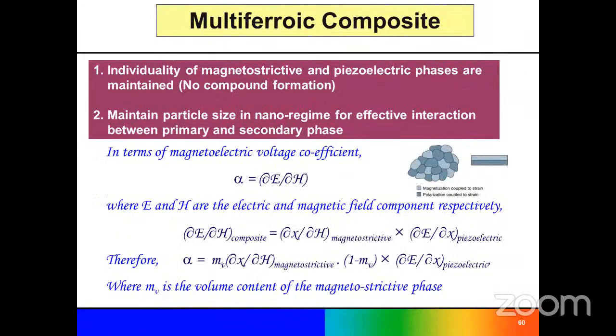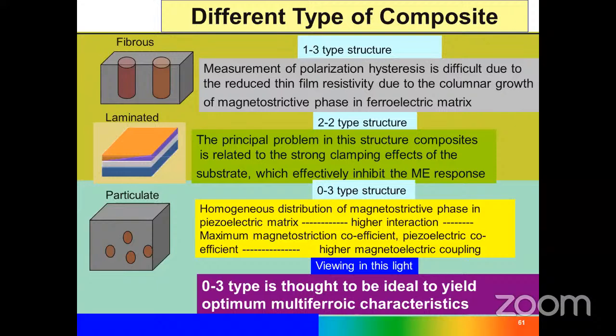For these reasons, we prepare composite materials where the magnetoelectric coefficient can be enhanced by tuning the structural morphology. There are different types of composite structures like 1-3, 2-2, and 0-3 types. In the 0-3 type structure, the piezoelectric matrix is distributed with the other nanoscale phase, which gives the maximum magnetoelectric coefficients. So we use the 0-3 type structure for memory device applications with this perovskite material.